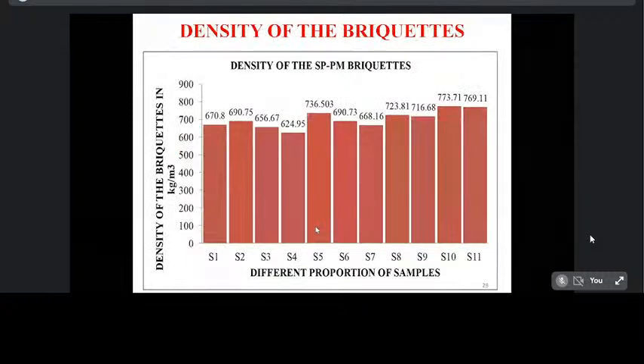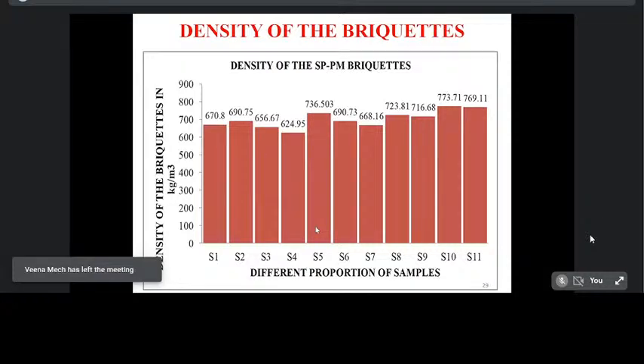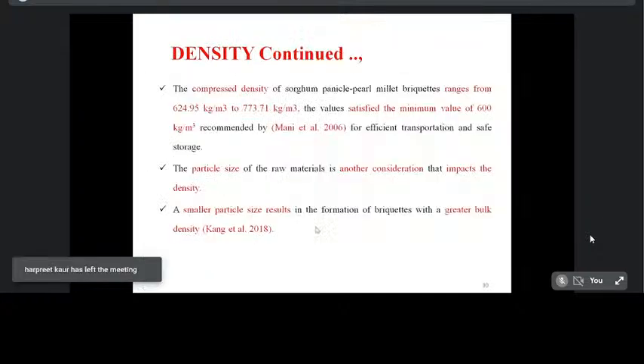Okay. So this image shows the different densities of the briquettes. Sample S4 has the minimum density value, that is 624.95 kilogram per meter cube, and sample S10 has the maximum density value, 773.71 kilogram per meter cube. So the compressed density of sorghum panicle and PM millet briquettes ranges from 624.95 kilogram per meter cube to 773.71 kilogram per meter cube. So it satisfies the minimum value. So definitely the density value required is 600 kilogram per meter cube, recommended by Mani et al. 2006 for efficient transportation and safe storage.